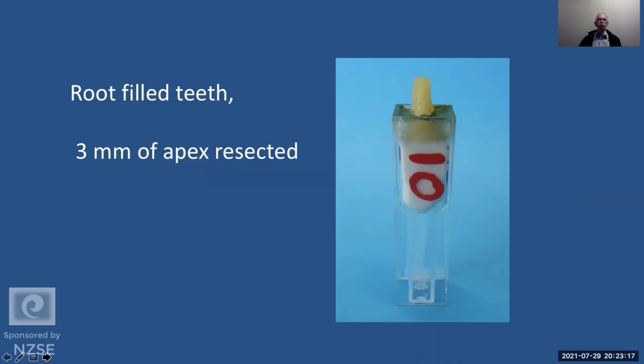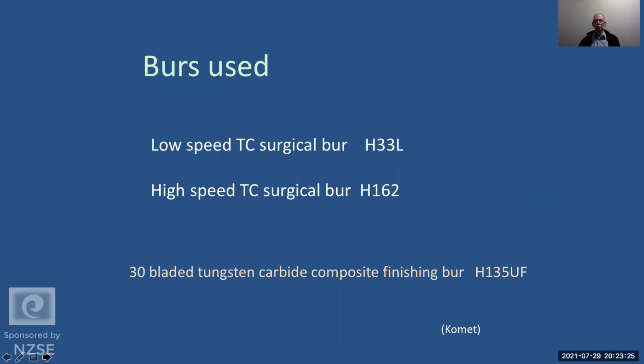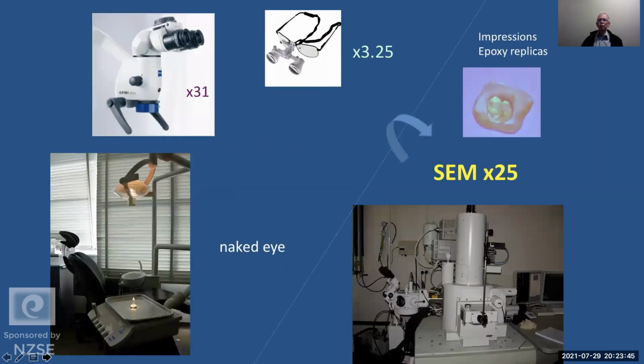So the experiment runs along with the root filled teeth, and you'll see here that about 3 millimeters has been resected. We resected them with different burrs. Now, one of them's a burr that you might expect the oral surgeons to use, and one of them's the 30-bladed tungsten carbide composite finishing burr, which is very difficult to say quickly. 30-bladed tungsten carbide composite finishing burr. And we got some amazing results.